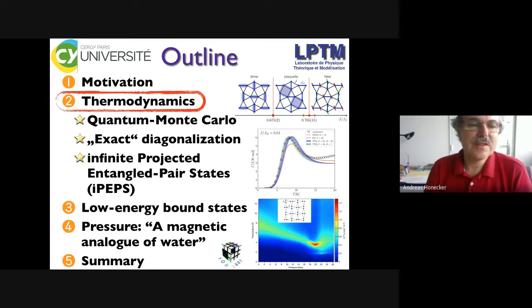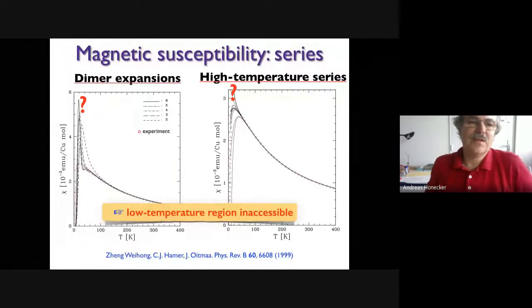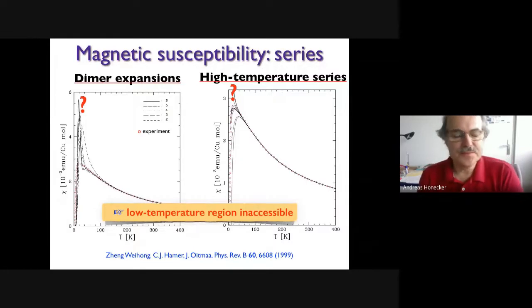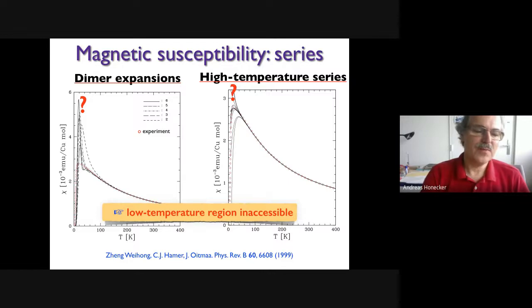Okay, now let's start with the methods. And so what is the issue? Of course, when this compound came out in 1999 or so, people immediately tried to explain the experiment that is shown here in red. One thing that they tried was series expansions, either high temperature series or dimer series. And you can fit the high temperature tail of the susceptibility here in these graphs nicely. But the point is, whatever you do, this breaks down in the low temperature region. So you really don't know what is happening in the low temperature region based on these thermodynamics. And that is actually the region of interest for us.